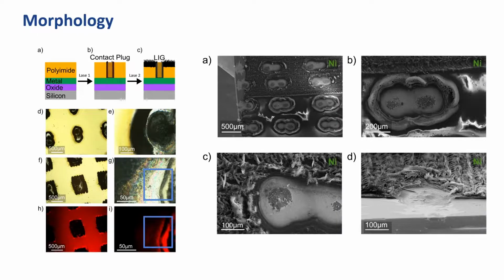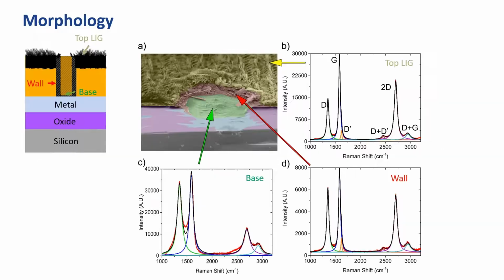Considering the scanning electron micrographs, we can confirm what we've already seen from the white light and fluorescent light images. There is a top surface laser-induced graphene material that is connected through a wall region to the base metal. This base is also covered in an organic material layer. The nature of these 3 regions is investigated through Raman spectroscopy. The different regions are colored accordingly, and characteristic Raman spectra from those regions are shown.